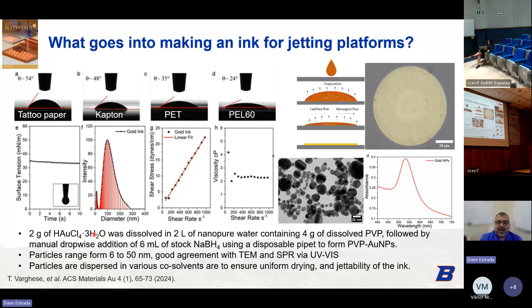Based on the kinetics of that reaction, we can tune the particle size by controlling the heat and the time of the reaction. We did some TEM analysis, and we find that our particles using this process are about 6 to 50 nanometers in diameter, and that corresponds well with the surface plasmon resonance mode that we measured with UV-Vis. And then we disperse this in various co-solvents. The details of all that are in this ACS Materials paper by Tony Varghese, a research scientist working in my group. So we look at various co-solvent systems to get the right viscosity and surface tension to tune into that printable window.